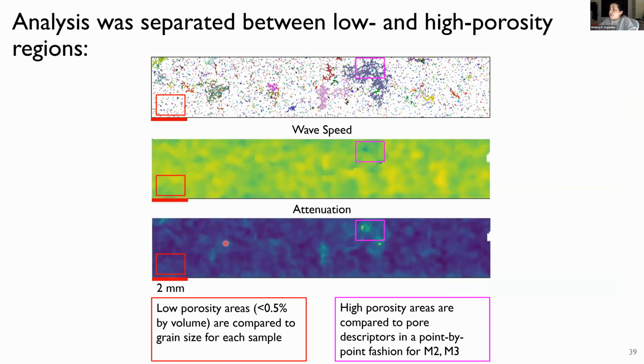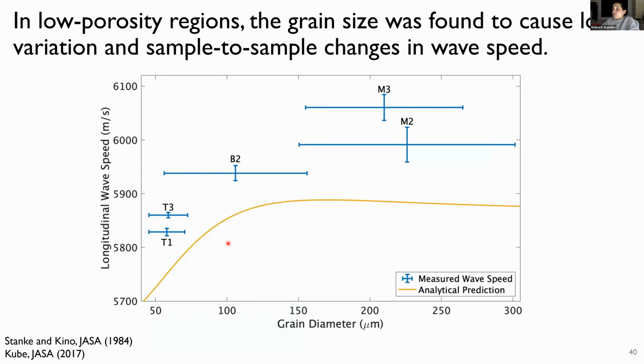In order to do that, we separated our analysis between low and high porosity regions. The way we defined this, just for the purpose of this analysis, was we said anything less than 0.5% by volume is considered a low porosity region. So we separated our data relative to the voxel size that we were able to obtain from the transducers we were using and the spatial resolution of the maps that we collected. And then high porosity areas would be anything where the porosity in that volume was greater than that 0.5%. And then we went ahead and calculated some pore descriptors based on the XCT data that we could then directly correlate to our ultrasonic parameters.